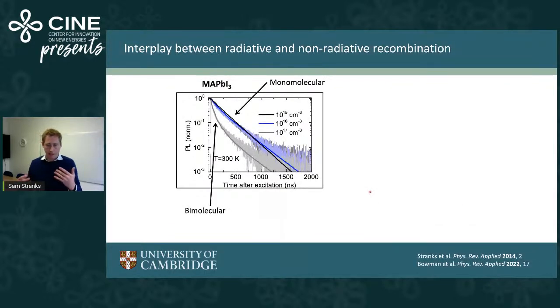So we can also understand the carrier recombination in a bit more depth. So this is here looking at photoluminescence decays again over time after excitation, and looking at different excitation densities, so different numbers of carriers generated initially. And what we can see is that at the lowest fluences, we see this monomolecular, so it's an exponential decay. So on this log plot, it's a straight line. But as we get up to higher injection density, we start to see a bimolecular recombination. So it's something that's no longer first order.